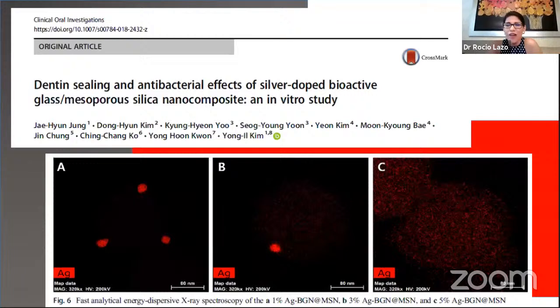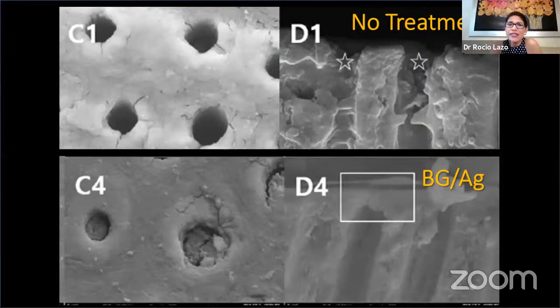Okay, another thing, talking about this new generation of glass ionomers with strontium. Do you remember that the problem with SDF is that it should not be too close to the pulp because the silver may cause pulp necrosis? But the silver is great because it is, first, antibacterial and, second, an inhibitor of the metalloproteinases. So in this case, I will present to you a glass ionomer that has strontium and silver. It's perfect because it's going to work better, and it's the Riva Silver. The problem with the Riva Silver is a little bit the color, okay?